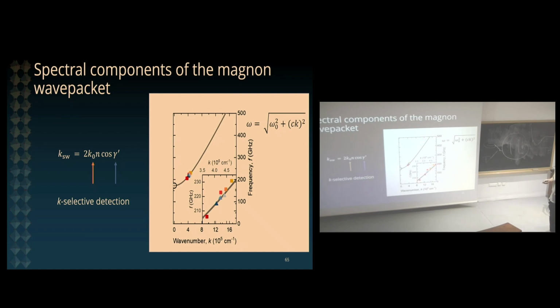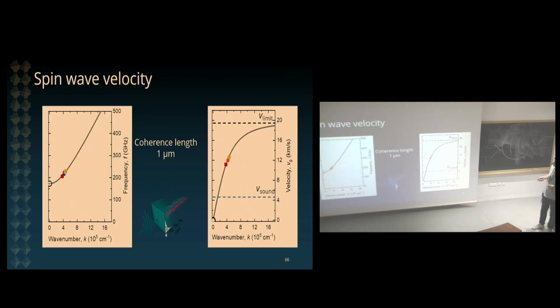The line that you see on top is not a fit. The line on top is the spin wave dispersion of this dysprosium orthoferrite that is known from literature. And this convinced us that we're actually detecting various components. And so this type of experiment also allows us to establish the propagation speed through the derivative of the dispersion, and we see that these components of the wave packets are traveling at a speed of the order of 12 kilometers per second. So this is 3 times the speed of sound in the material, and we're only a factor of 2 below the theoretical limiting speed that is possible for the propagation of the wave packet.